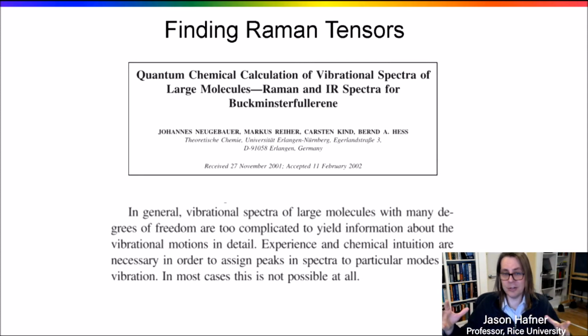You can do lots of tricks. You can deuterate and get a shift in the peak due to the change in the weight of the hydrogen to the deuterium, and the carbon-13. A huge amount of effort. I'm not saying it's all just guesswork, but I'm saying that the word assign is there because it's hard to know them. And because they want to calculate them, well, how? Right? It's really hard. It's a quantum system. It's a big molecule.